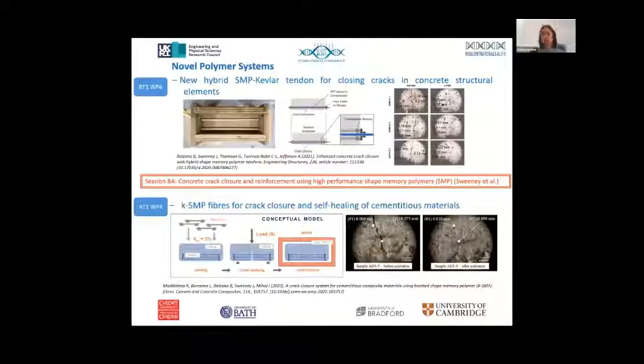We have, as a different strand of our work, our novel polymer systems, and we work quite closely with Bradford University on the development of these. And the first is our shape memory polymer Kevlar tendons. These comprise a strong Kevlar core, which is placed within tension within a PET shape memory polymer sleeve. This outer sleeve constrains the pre-stressed core until it's activated via heating, at which point the tensile preload stored in the core and the shrinkage potential of the PET sleeve are released.